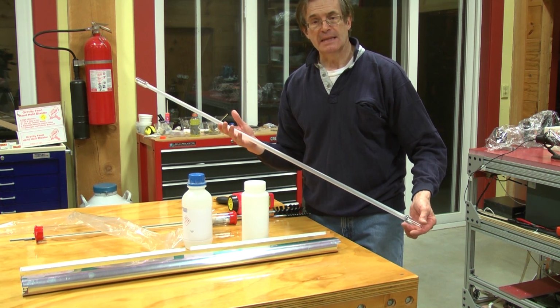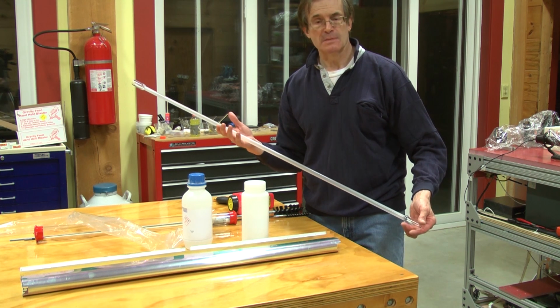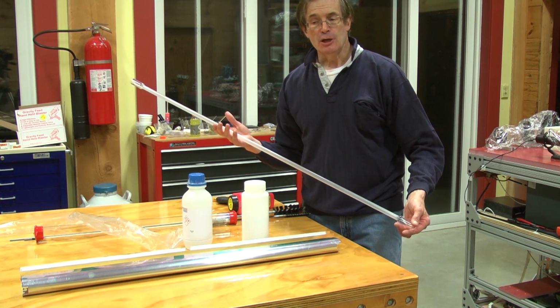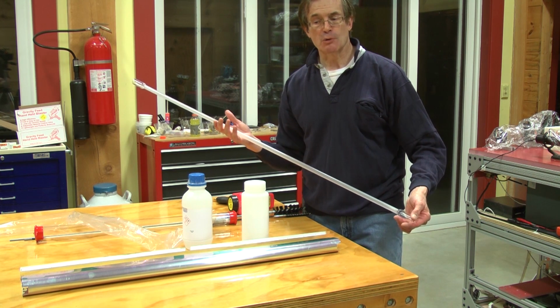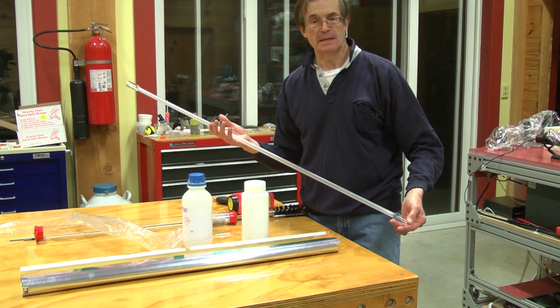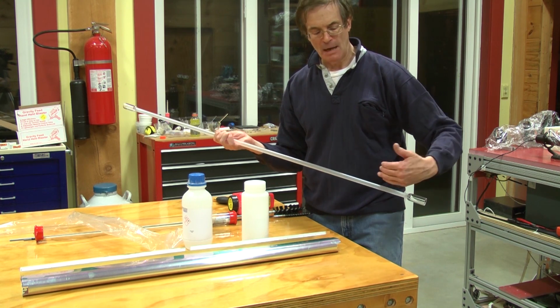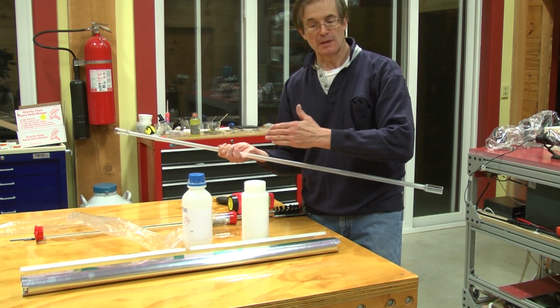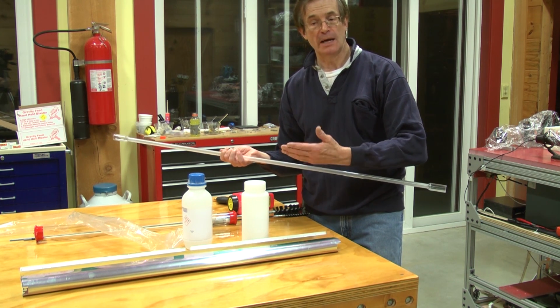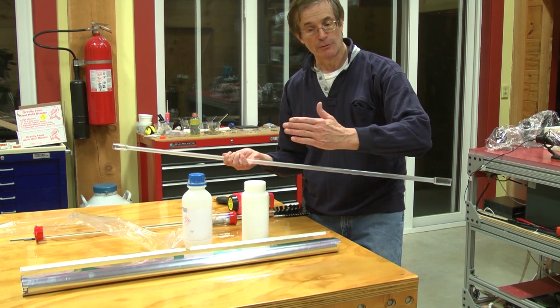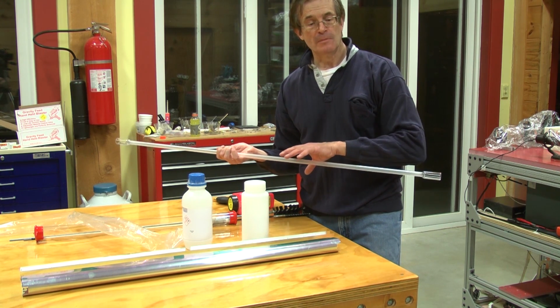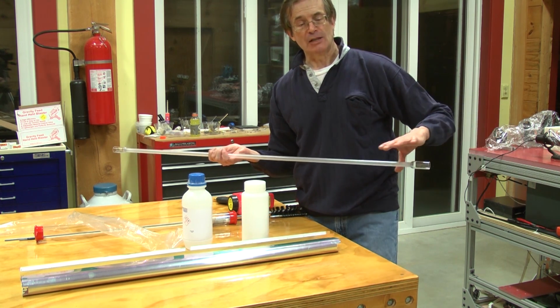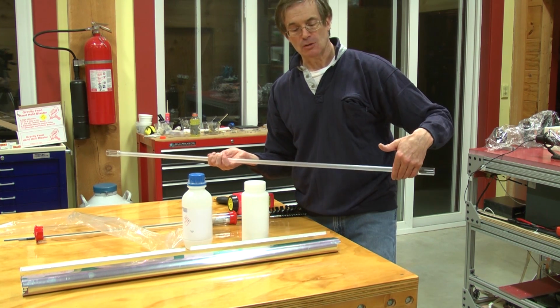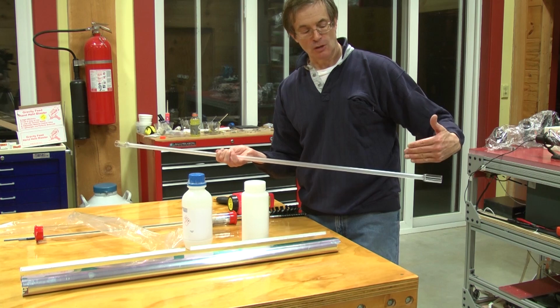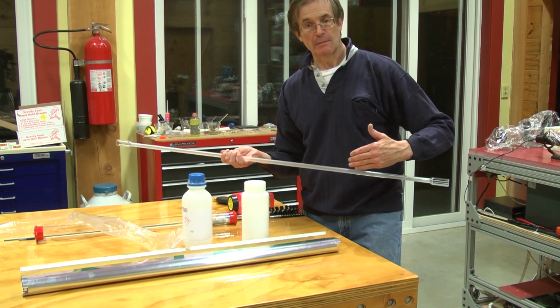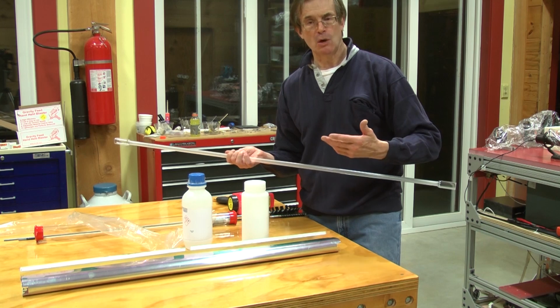The reason for that is in any kind of a dense material, whether it's a rod or whether it's a liquid, there is a potential for spurious types of laser ray paths that can pass through the tube, that can actually bounce within the tube, glance along the surface between the liquid and the glass, or in a solid rod, between the glass or the crystal and the outer air. And that can produce a lot of halo light coming out of the end of the laser. It can also deplete some of the excited state molecules that are needed to run the laser operation along the path you intend, by depleting them by these spurious pathways. They're called whispering modes or